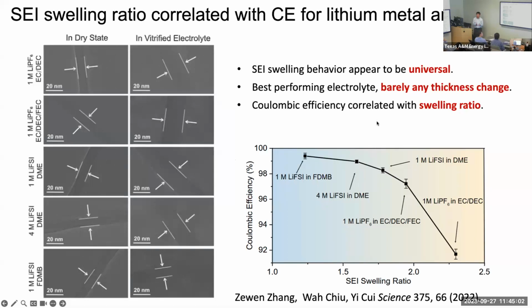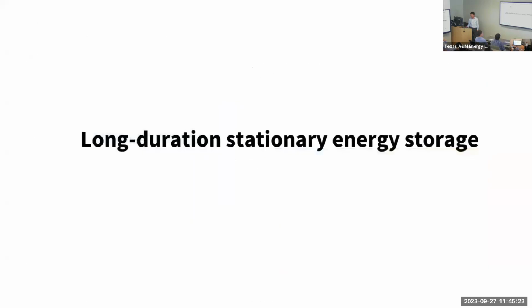It's also due to this different solvent molecule. The first solvation shell structure is very different. With a weakly solvating structure, it has more anion negative charge than the solvent molecule, then you build more inorganic in the SEI. So we correlated this completely. This is super exciting to me. So maybe the last couple of minutes, then I'll stop, right?